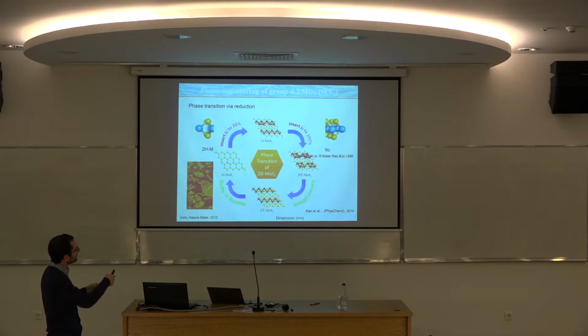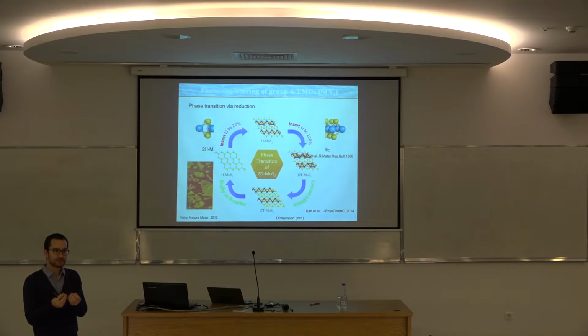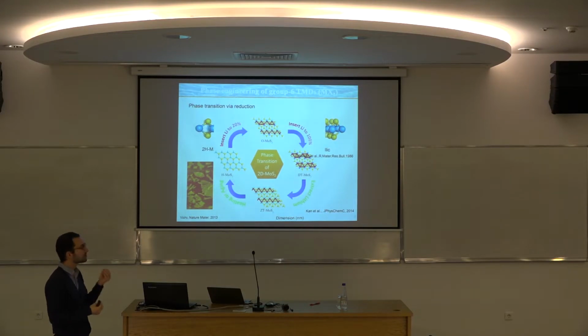Since you have a large excess of electrons, the nanosheets will have to adjust, and the most stable structure to accommodate this large excess of charge is this diamond shape that we have seen for ReS2 on my previous slide. And this material, this distorted 1T phase with diamond clustering of the molybdenum atoms, can later relax into a zigzag chain when you de-intercalate.